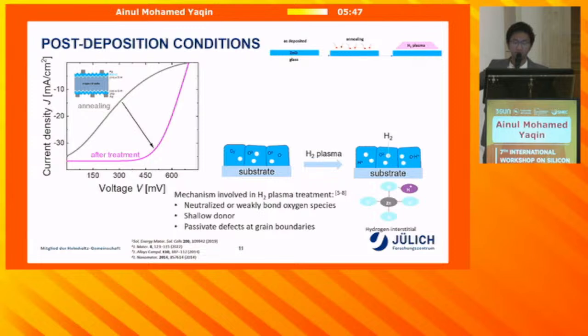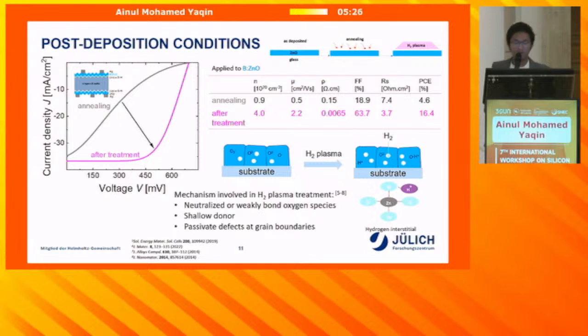So what actually happens with the hydrogen plasma treatment? With the hydrogen plasma treatment, you can neutralize or dissolve the oxygen species. You can also weakly bond the oxygen species, so then you have the carrier concentration back. The hydrogen can also act as a shallow donor, so you also have free charge carriers. The hydrogen plasma treatment is also known to passivate the defects in the material, which can improve the mobility. As you can see, after the hydrogen plasma treatment, we improve the carrier concentration back, and also our mobility.